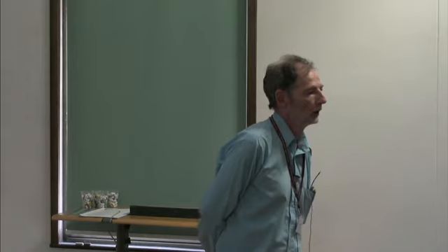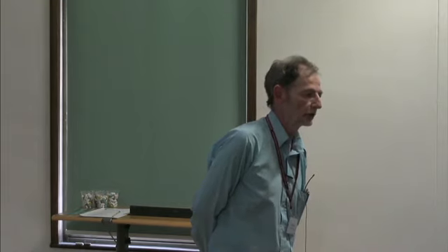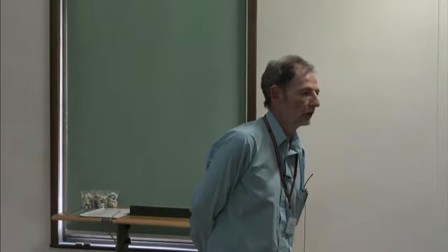So the experimental result by Dick James and Tom Shield, it's about creating this austenite-martensite interface, right? According to one of the theorems or propositions you mentioned, you needed to have the middle eigenvalue equal to 1, and the so-called cofactor conditions are also satisfied. So what they do, they just adjust these lattice parameters? That's right. Of course the lattice parameters depend on the composition of the alloy.